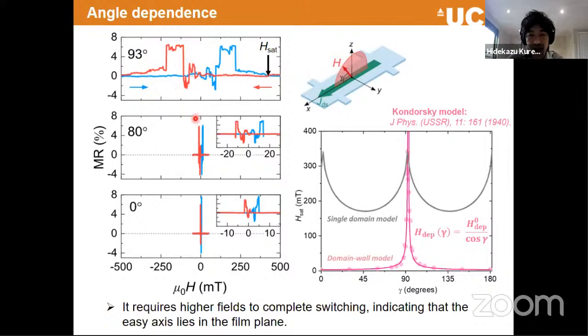And if you tilt this magnetic moment away from the out-of-plane direction, we can quickly notice that the width of this hysteresis is significantly reduced, and it continues toward the in-plane direction. That can match some picture of the domain wall. It's nothing surprising because this is a macroscopic, micron-scale sample, but it's nice to see that the quick decay represents the domain wall switching mechanism being heavily involved, and that was picked up by our magnetotransport. Right, okay. And also that guarantees that the hard axis of this material is out of plane compared to in plane. That is different from a bulk sample. I'll come back to this point in a minute, but I just want to mention it here.